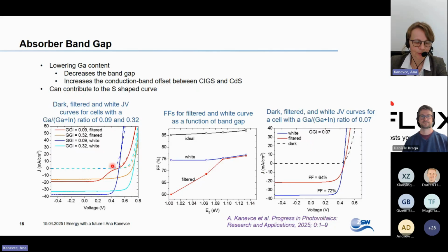Here are JV measurements, white shown with blue, so with unfiltered light, and also with a filtered illumination of two CIGS solar cells. 32% gallium, this is a standard band gap CIGS solar cell, and then with 9% GGI, this is a low band gap cell. Now the white illuminated, the non-filtered curves are standard, they're diodes, well behaved. The filtered ones, the standard bandgap cell is a diode curve, is good, and then the low bandgap cell has an S shape. Sometimes this S shape is very pronounced. Other times, for example, like in this example, the fill factor goes down to 60.